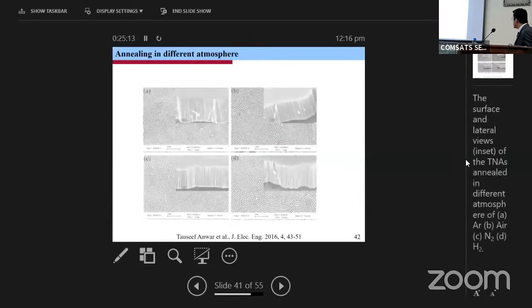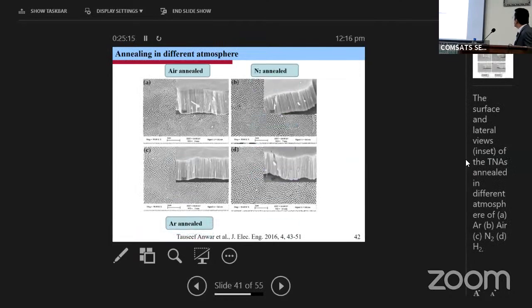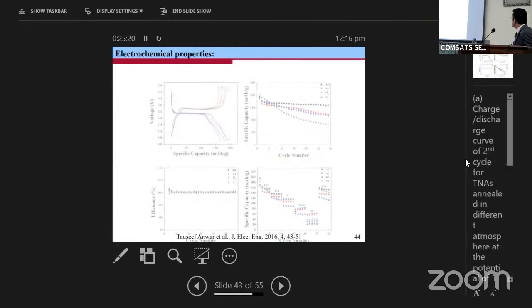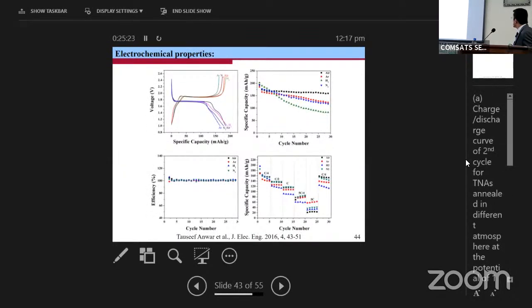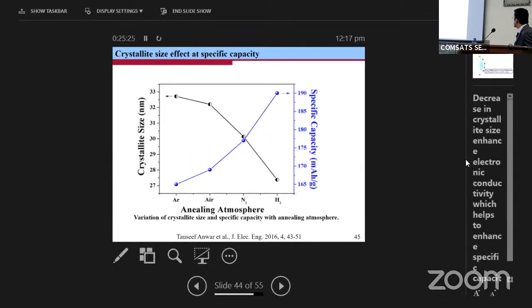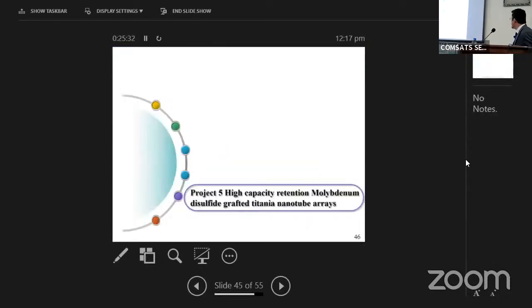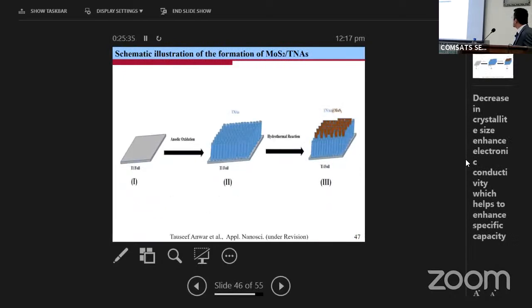And in this, I annealed these titanium dioxide nanotubes in different environments, and I studied its effect. So in different environments, air, nitrogen, argon, the crystallite size was studied, and this is the crystallite size. It shows how specific capacity of the lithium battery anode material increases with decreasing crystallite size. This was a scientific study, so maybe a lot of people will be interested in this. If someone is interested in this, they can ask me. I have all this data.